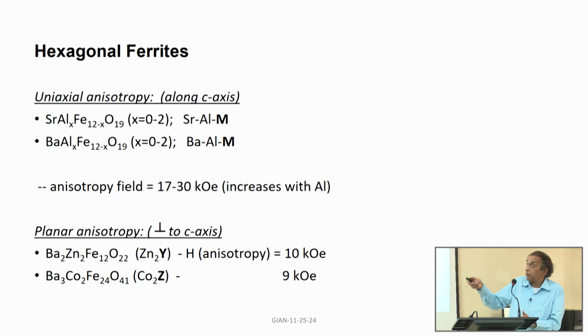So, that means there is a built-in magnetic field in the composite itself. That is where the hexagonal ferrites are the key element in this whole scheme. If I have strontium or barium hexaferrite with a very high uniaxial anisotropy field, it has a built-in magnetic field which will act as a bias field. That will eliminate the need for an external permanent magnet or something else. So, that is how you overcome these difficulties with the use of hexagonal ferrite.